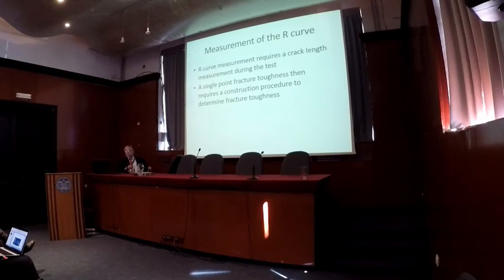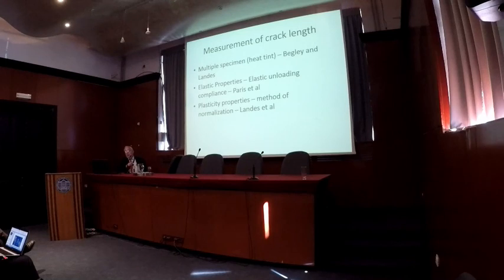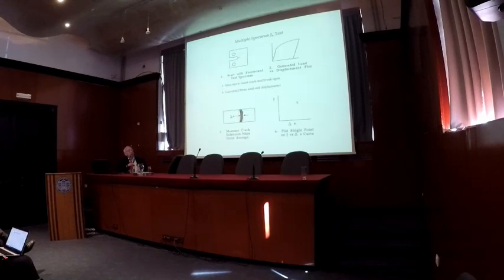So back to the R curve. If you're going to do R curve analysis, you have to measure crack length during the test. And then to get a single point that people might want in their structural evaluation, a single fracture toughness, you have to pick a point on the R curve. So here are some of the methods that people have used. The heat tint method that we developed at Westinghouse, something called elastic unloading compliance that Paul Paris developed, and then the plasticity parameters we call normalization that we developed when I was at University of Tennessee.